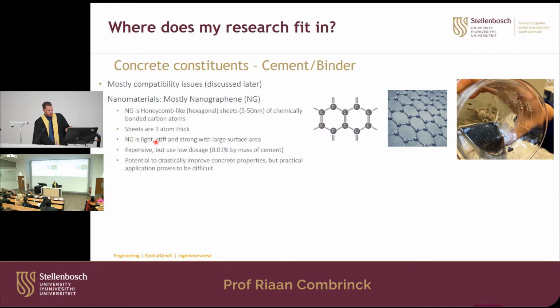It's very light, stiff, and strong with a large surface area, but it's also expensive. But we add a very low dosage of it. Admixtures you normally add at 1% by mass of cement, but here we can add only 0.01%. And if you calculate the number of particles, that's millions of particles, actually more than the cement that you add. So small, these particles. There's potential to drastically improve concrete properties, but the practical application remains difficult because the particles are so small, they tend to flock together. So the real challenge is deflocculating and getting those nanoparticles spread evenly in your concrete.